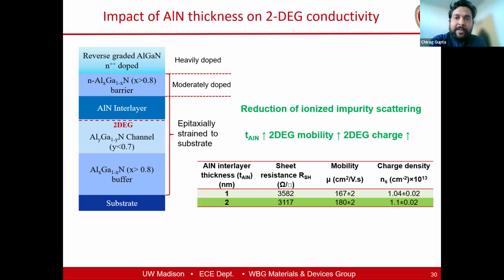ohm per square. This is again very close to state-of-the-art results that are out there, and this is roughly 10 times more than gallium nitride sheet resistance. But the idea is that these materials have high breakdown field, and with high breakdown field, they would ideally compensate for the reduction in mobility or conductivity. So all in all, with on resistance and breakdown, which is the Baliga figure of merit, you would see an overall win in these designs. And that is something that needs to be demonstrated at the moment.